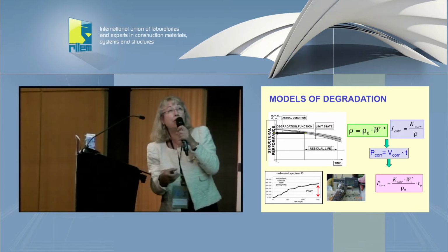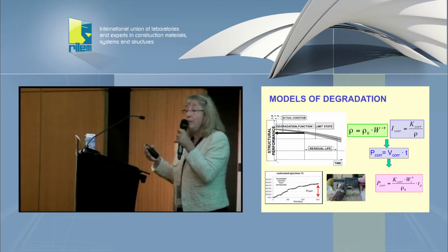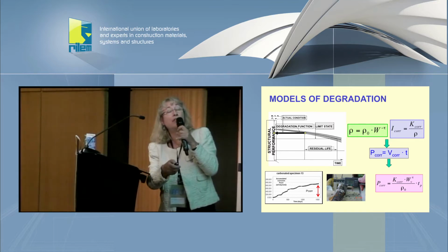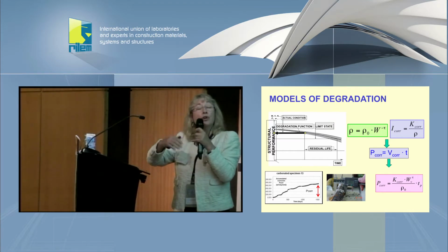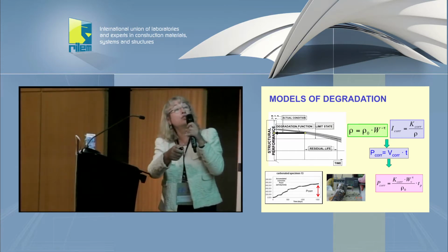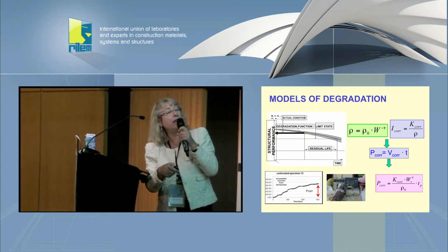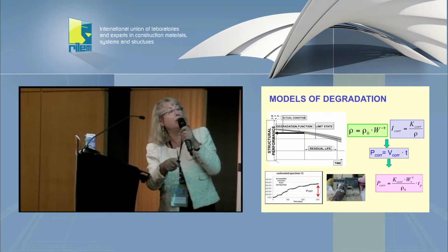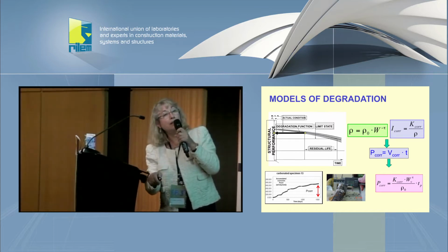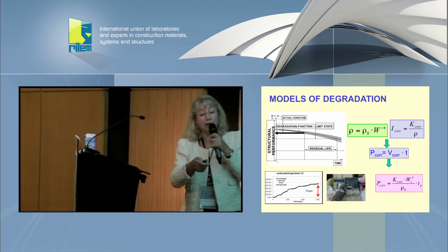And this is what happens in the south of Europe, in my country, because we have dry periods of long time. In that case, in spite of high temperatures, we have less corrosion than the Nordic people, who have much more time of wetness because the water remains inside the pores for a longer time. Just going into the effect of the ambient, we did a lot of work on this, and the corrosion rate changes, of course, depending on the rain events, on the temperature, and so on. But if we just plot that as accumulated corrosion, that is the amount of loss in the diameter with time, that is not so dispersed. It is progressive, of course, the loss in section, and going into the events of summer and winter, it's possible to have more or less what is in the conceptual model of a constant corrosion rate.